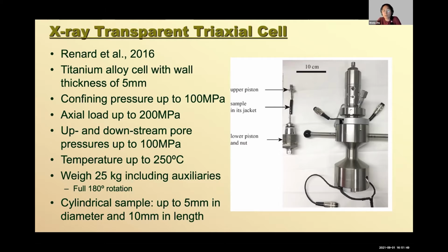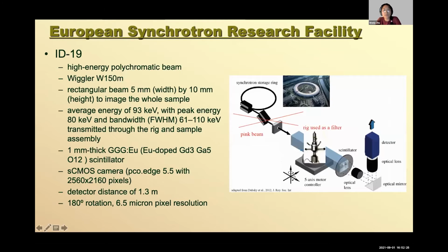This allows us to apply a confining pressure up to 100 MPa and an axial load up to 200 MPa. And important for my research, we can have upstream and downstream pore fluid pressure ports, so that you can actually have flow. Fluids can be water, CO2, or other aqueous fluids flowing through the rock, so that you have chemical and mechanical coupling. This whole cell experiment was conducted at ID19 in the ESRF.